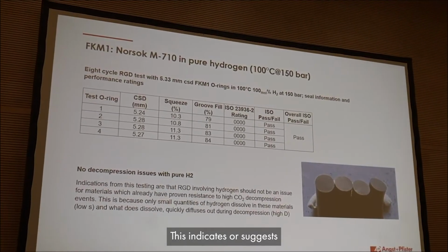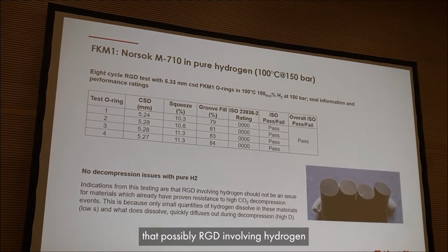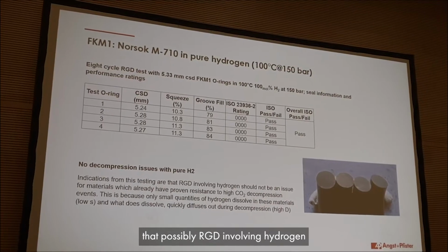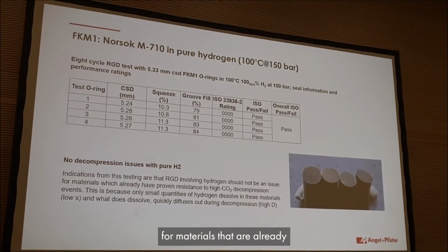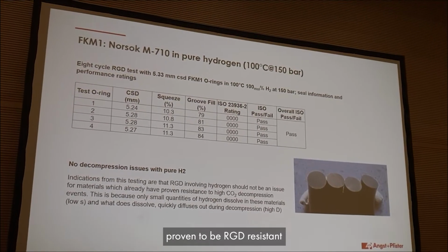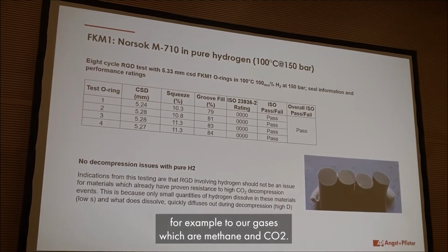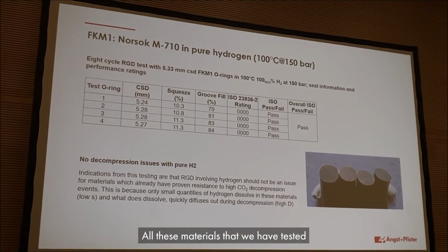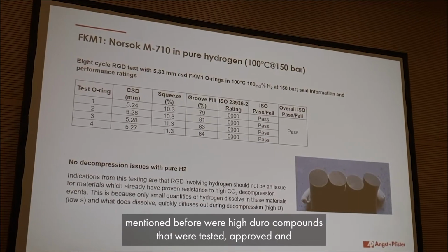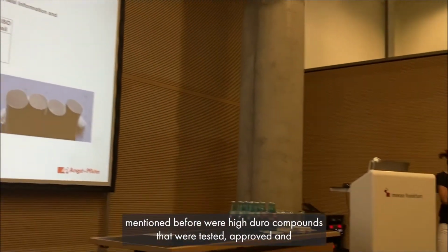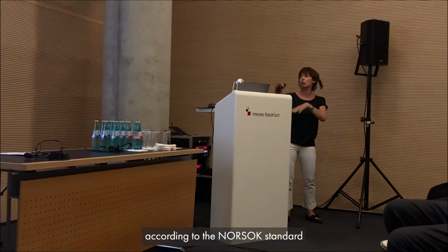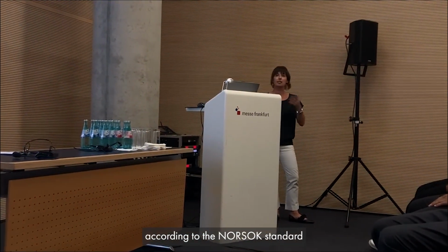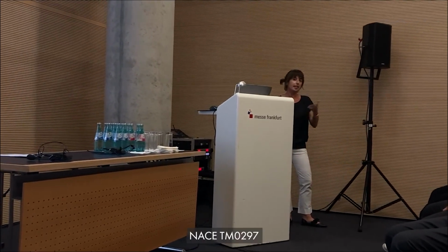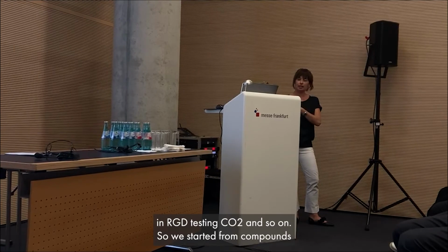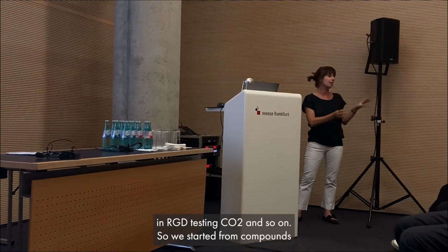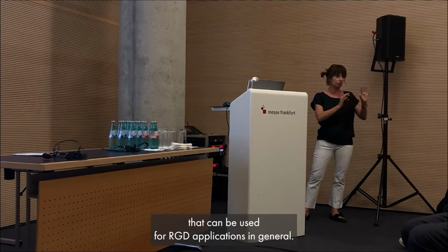This once again would suggest that possibly RGD, or rapid gas decompression, involving hydrogen should not be an issue for materials that are already proven to be RGD resistant to, for example, other gases, which are usually methane and CO2. All these materials that we have tested, as we have mentioned before, were 90 Duro compounds that were tested and approved and proven to be RGD resistant according to the NORSOK testing standard or the NACE TM0297 in RGD testing in CO2 and so on. So we started from compounds that can be used for rapid gas decompression applications in general.